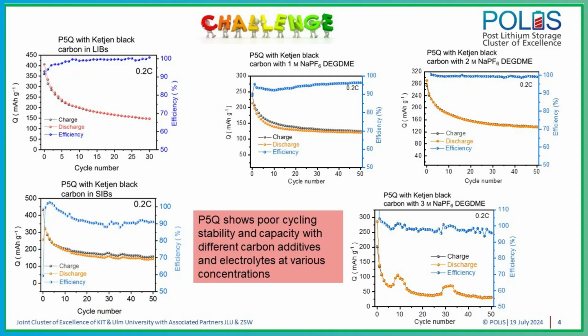The biggest challenge that we have faced is to inhibit the dissolution of this pillar-5-quinone material into the aprotic organic electrolyte and to increase its electrical conductivity of the electrode. So in order to overcome its electrical conductivity issue, we have tried several conducting carbon such as Super P, Ketjen black, carbon black, and even we have tried a variety of electrolyte to stop the dissolution of pillar-5-quinone into the aprotic organic electrolyte. This small molecule pillar-5-quinone is highly dissolvable in most of the electrolyte that we have tested. So during our initial tests, because of its high dissolution problem, the cycling stability of the battery and its capacity was very poor.